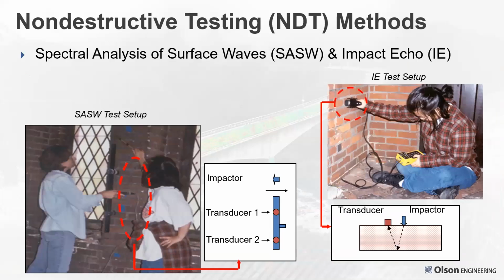So spectral analysis of surface waves is shown on the left, and the impact echo is shown on the right. Surface waves is basically an impact with a small hammer between two displacement transducers on an SASW bar, and you measure the velocity of the surface wave, and it is affected by the cracks, the materials, and competency behind it and between the transducers.